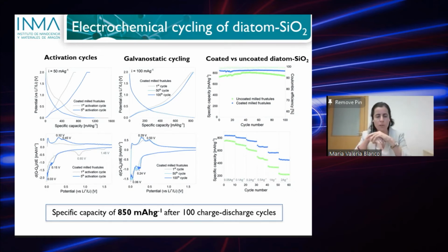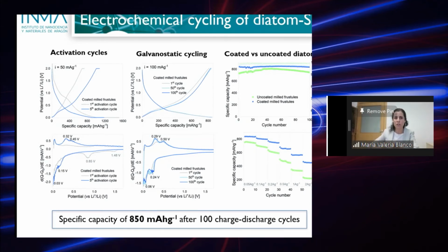So as you can see on the left, we had to perform some activation cycles at the beginning, because we were seeing that upon cycling, for each electrochemical cycle, we got a higher capacity each time. So we made very slow charge and discharge cycles to see what was the maximum capacity that we can get from this material. And after 5 cycles, we reached the stable capacity. So we call these activation cycles, and then once we reach this capacity, we speed up the cycling a bit, by increasing the current rate, and then we perform 100 cycles of charge and discharge to see how the material responded.